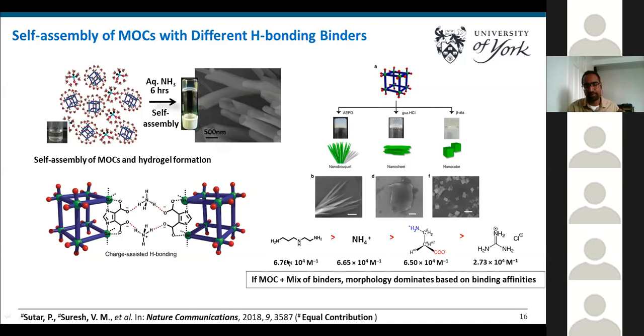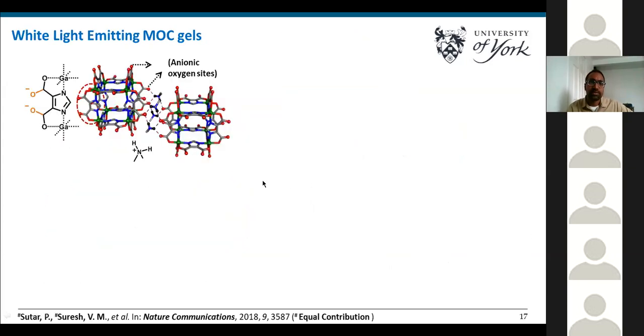For example, if we take aminoethyl propanediamine and guanidine hydrochloride and mix them together into a solution of MOC, we ultimately see the formation of bouquet-like nanostructures over the nanosheets, because the binding affinity of aminoethyl propanediamine is extremely higher than guanidine hydrochloride. So we want to create a white light emitting gel.